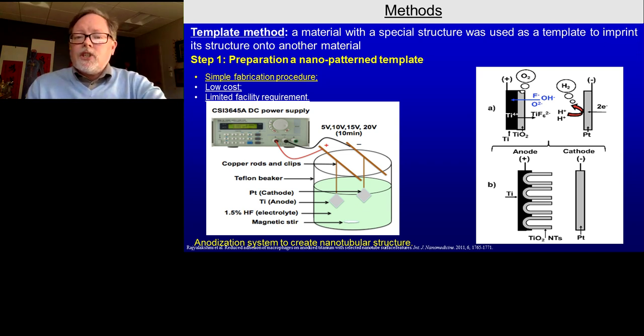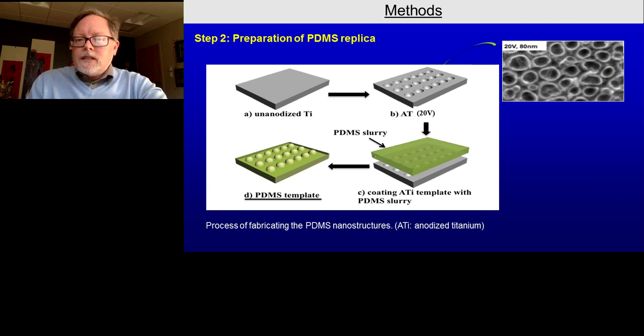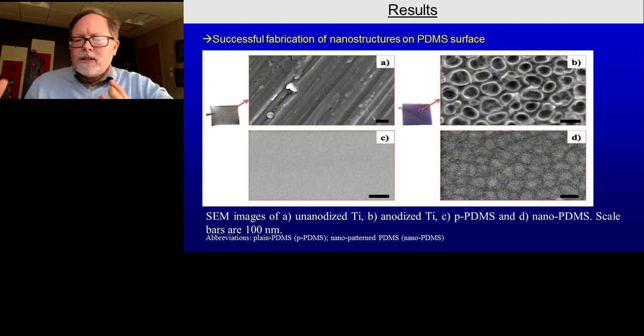And again, our material we used to copy roughness onto the polymer was our anodized titanium, the same material that I just discussed for that amputee model. We followed an anodization process. We were able to generate nanoscale features similar to what I showed you before. Here's a picture in the upper right of these unique nanoscale features we create on titanium. That roughness can then be copied over to a polymer by simply pouring a mold, making a mold of this titanium, and then pouring polymer like PDMS, which is polydimethylsiloxane, into that mold.